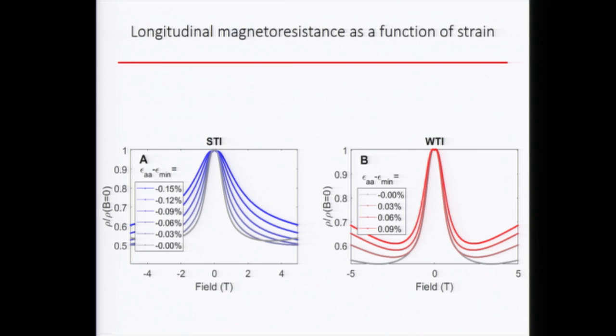Yes. Wouldn't that also just be a different density in the odds of the Hall? So for this, we never see any semimetal dHvA. Yeah, and then according to that carrier density, some higher carrier density samples, which you measure from the Hall effect, have much higher carrier density than this. So if you just infer from the carrier density, the quantum limit should be around 0.5 or 1. Right, so you're already in the last Landau level. Why is it that you're saying the mobility is not good enough to see it in both fields? Right, so I think you already reached the quantum limit before omega_c tau is large enough. Yeah, I think that's what happened.